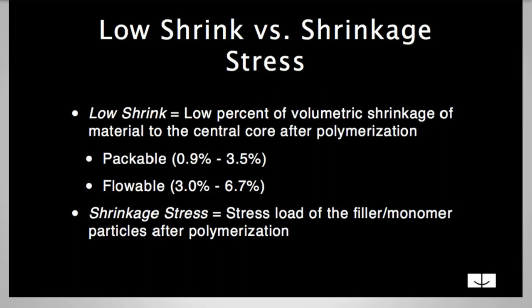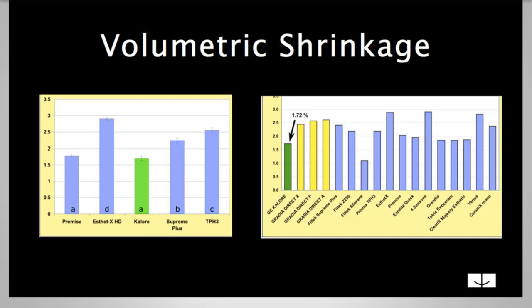So here are two studies. The one on the left is a third party. The one on the right is an in-house study, just showing Kalore against some of the other competitors about volumetric or polymerization shrinkage. And it is pretty low, about 1.72%. It's lower than most packable composites. You see Filtek low shrink is super low shrink.